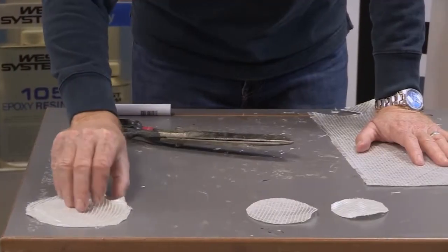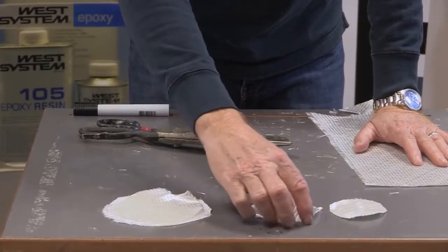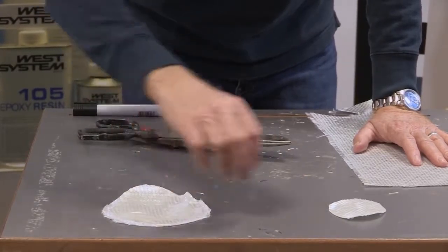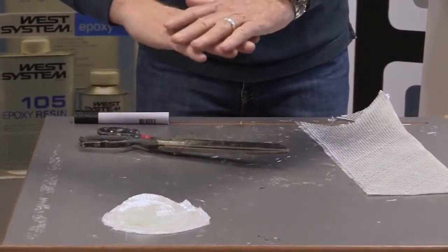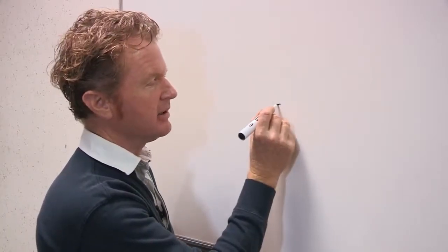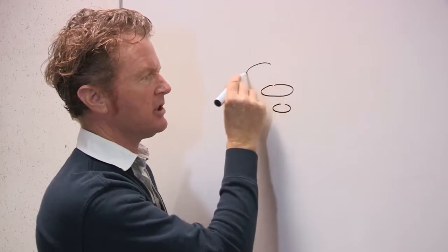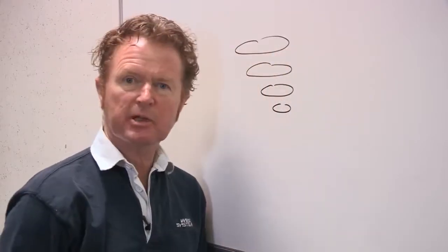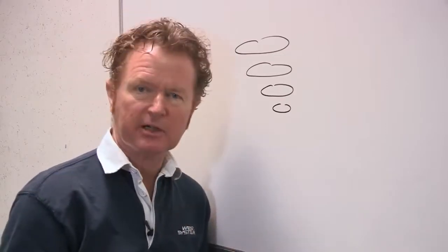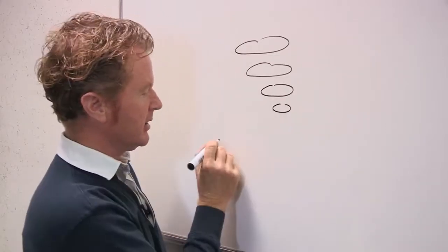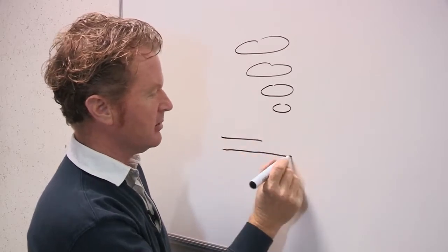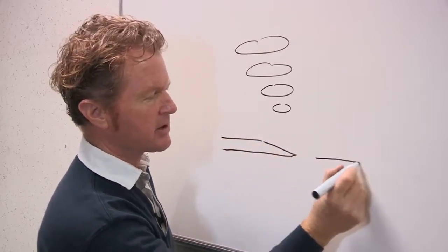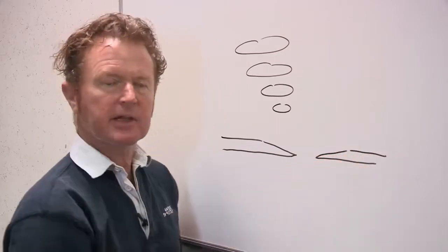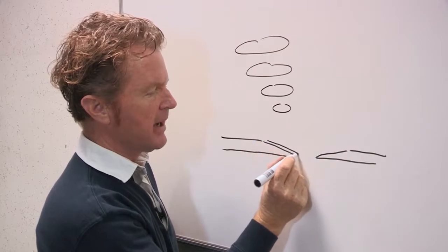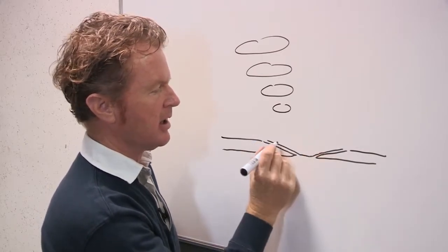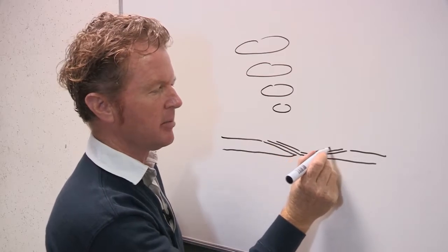It's important also to get the fibre to line up. So I'm just lining up the stitching and then all the fibres will be orientated for a very, very strong repair. Now you have a series of different sized patches, four in total, to build up to our laminate thickness. Now you might ask yourself, which order do these go in? Well, actually, they always go with the biggest patch first. And the reason that we do that is because the biggest patch gives you the maximum contact surface of any one of these patches.